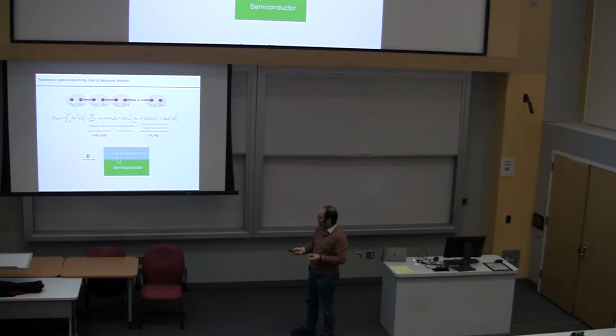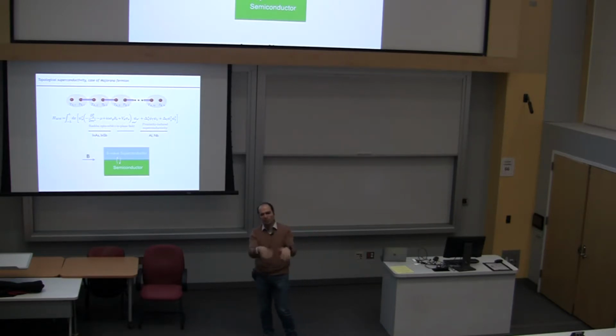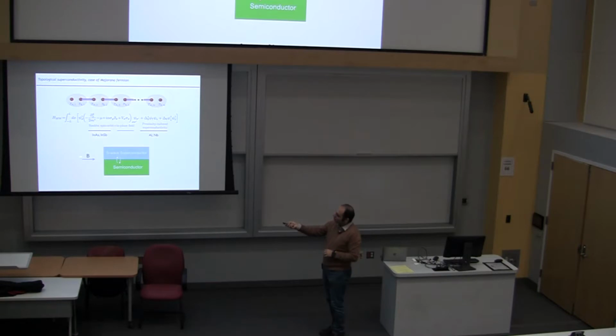And then somebody said, okay, we cannot have all of them in the same material. Let's put the one with Rashba spin orbit here, and then put the S-wave on top of it. If they are really close and the interface is perfect, maybe these guys talk to each other, and you cook up that Hamiltonian at that interface. But now the interface becomes extremely important, because you don't want any impurity. It has to be smooth, uniform, almost perfect, right? Then you apply an in-plane magnetic field, and you have your Hamiltonian at that interface, and you can study it, right? Instead of going after a new material synthesis with interfaces and surfaces, we try to simulate this Hamiltonian.